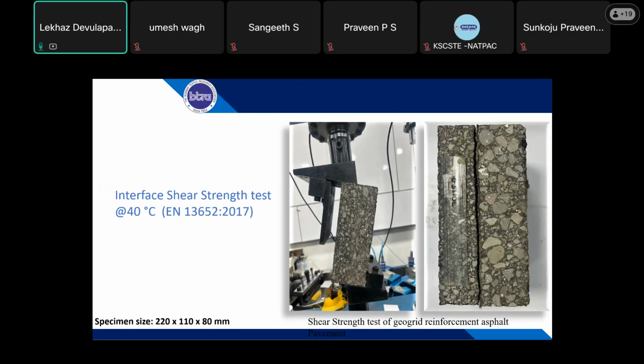Two years back, we started with different dosages of tack coat and different types of tack coat, by taking one geogrid, and we also tested at different temperatures. In this talk I am showing only the 40-degree temperature, but we did this test at 23 degrees with different tack coat dosages, starting from 0.2 to 1.2 kg per meter square with an interval of 0.3 kg.